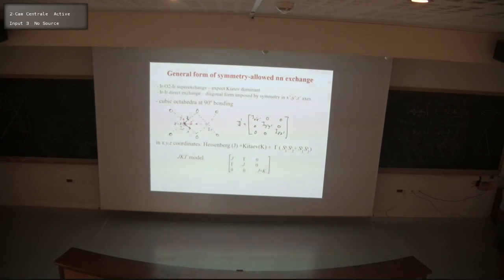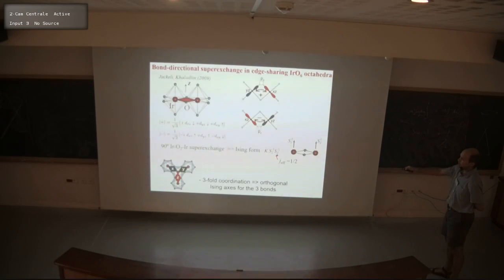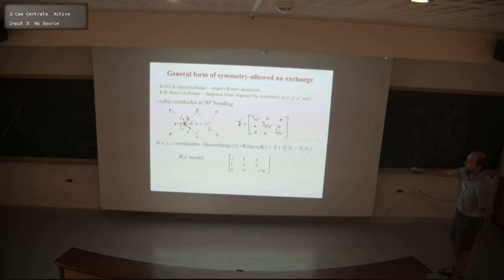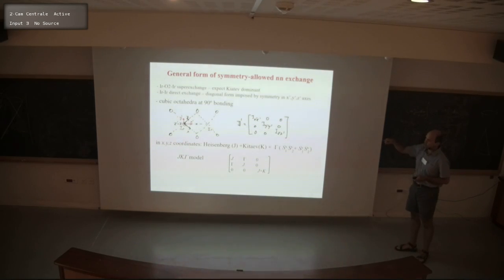However, the 5d orbitals are quite extended, and there's also a possibility of direct exchange between the 2 iridium sites, not involving the oxygen. And here the processes are quite different, and the most general symmetry allowed form for the Hamiltonian is actually diagonal in the special axes where x prime goes along the bond, z is orthogonal to the plane of the bond, and y is the other direction. There's no symmetry relating all of these 3, so in this coordinate system, the most general form for the exchange contains independent values for the xx prime, yy prime, and zz prime.